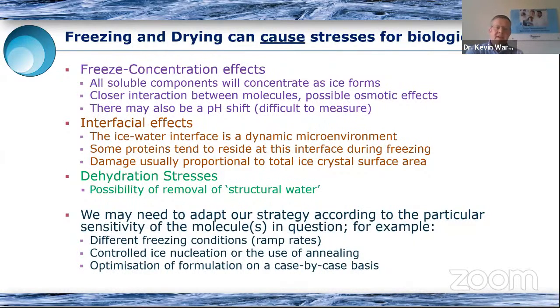And so at the bottom, as you can see here, we're going to need to adapt our freeze drying strategy and even our formulation strategy according to the sensitivities of the molecule or the active material in question. So different freezing conditions, maybe controlled nucleation, which we know is available commercially on some of the SP Scientific freeze dryers now, or the use of annealing to try to make things more thermally stable, and maybe to adjust the formulation. So everything, as much as we have some good knowledge over the last several years on the freeze drying of biologicals, we still need to approach them on a case-by-case basis.